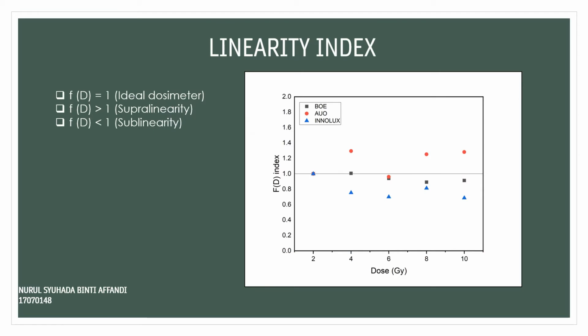The third is the linearity index. The linearity index for the ideal dosimeter should have FD equal to 1. It should also be noted that FD more than 1 indicates supralinearity, and FD less than 1 indicates sublinearity. It can be observed that BOE and Innolux show sublinear behavior, while AUO shows supralinear behavior, except at the 6th gray, where it shows a sublinear behavior.